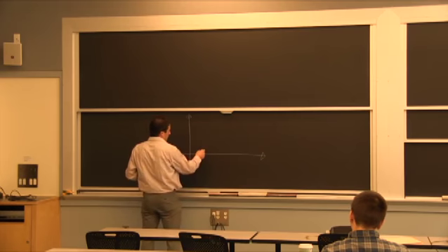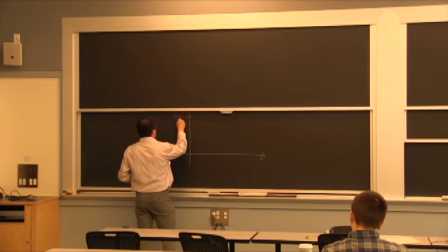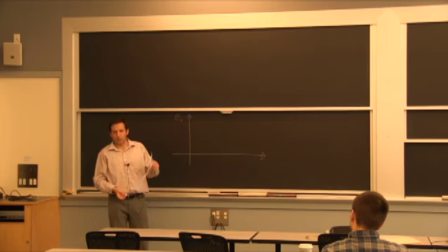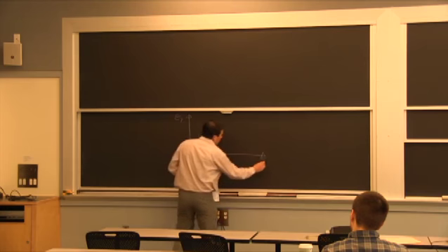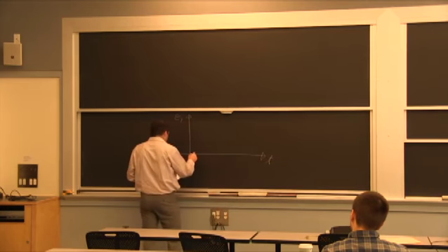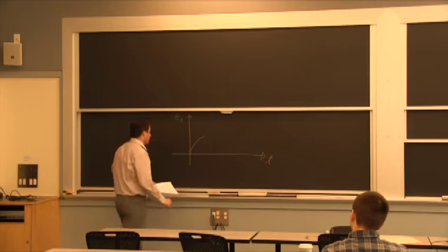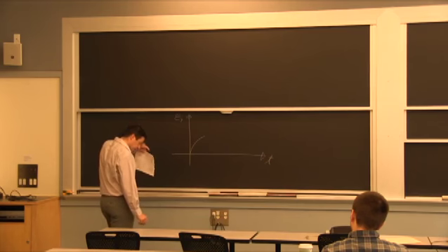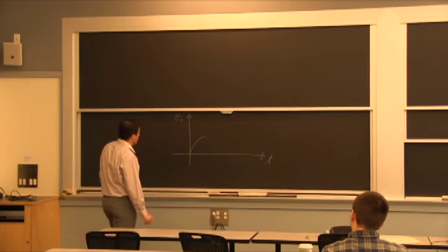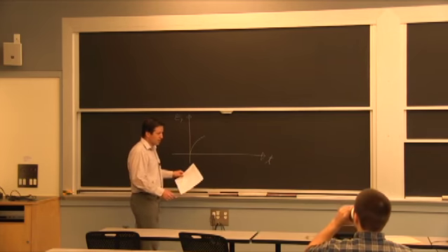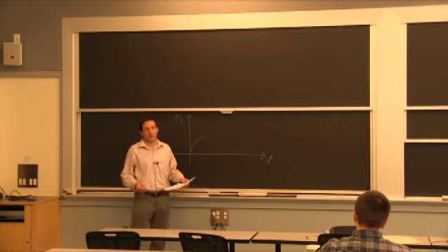initially, so say we look here at the, I'm going to call it the plastic deformation. So obviously when you apply the load, you have Hooke's law, you have some elastic deformation, and then after that, over time, you get that plasticity. So you start initially, and your rate of deformation is going down. This is concave shape towards the bottom. It's a negative convexity. And what happens is you are exhausting the easy sites for deformation.